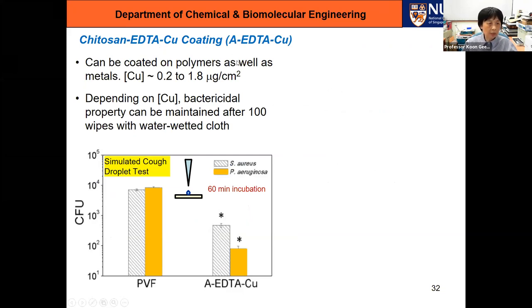And this coating can be put on polymers, it can be put on metals, and the amount of copper that's loaded can be varied. And depending on the amount of copper, the bactericidal property can be maintained after 100 wipes with a piece of cloth that's wetted with water. If the concentration is too low, then we'll lose the bactericidal property. But if it is maintained at a certain level, then we can preserve the bactericidal property.